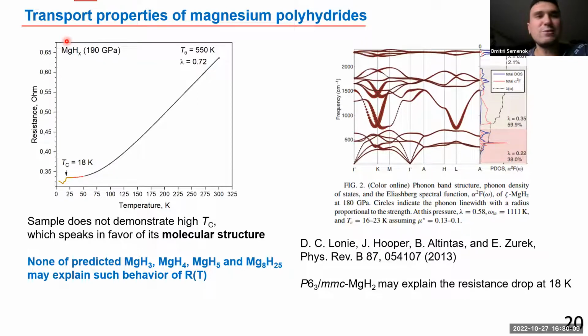I mean, how the resistance of these magnesium hydrides behaves under high pressure. At 190 GPa, you see that the behavior is completely metallic, and down to 18 kelvins there are absolutely no signs of superconductivity in these compounds. Only at around 18 kelvins do we see a partial drop of resistance. It's not a proof of superconductivity, but it's like a tip, like we need to pay more attention to this field.